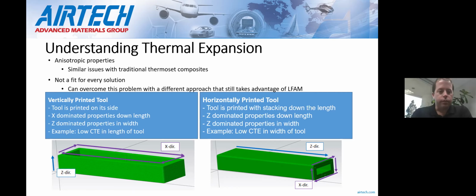So because it's an extrusion, you get these anisotropic properties. This is in some ways very similar to traditional thermoset composites, but everything's kind of turned 90 degrees. So when possible, obviously we'll do our best to control the CTE, which is typically lowest in the X direction, which is the extrusion direction, and Z would be the stacking direction.